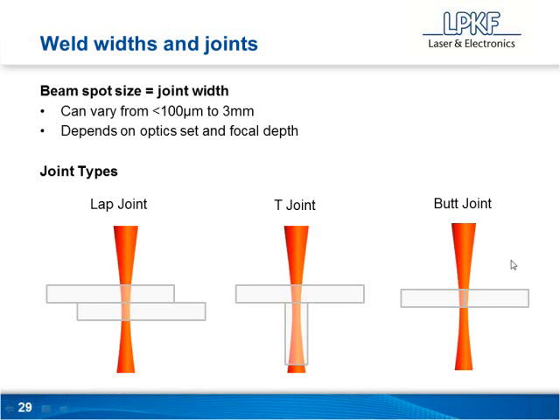whereas with regular through transmission laser welding, you'd only be seeing melt from one side, so we'd have to bring the laser in at a funny angle, and it just wouldn't work. But because of the way that the plastic's volumetrically heated and then pressed together, it works almost more like a hot plate weld or an IR weld. So in this instance, butt joints, although they can still be tricky, are very much possible.